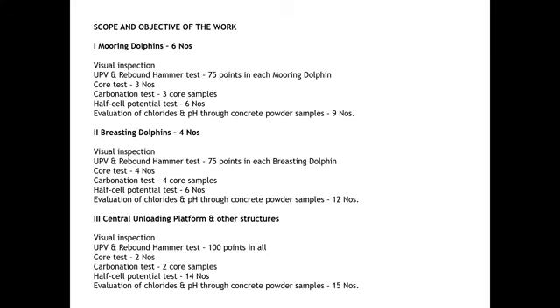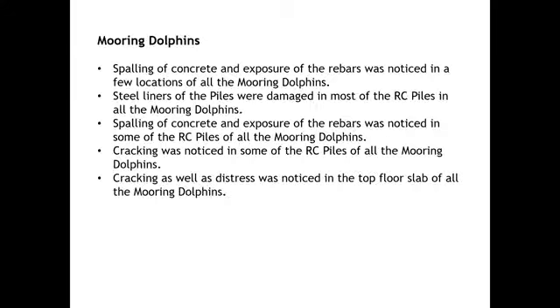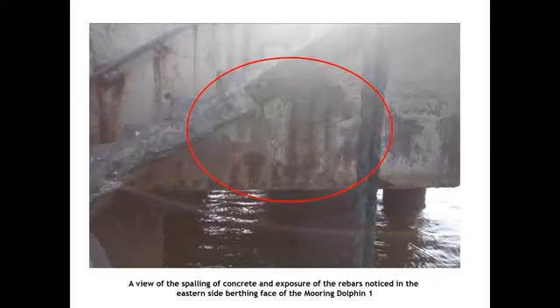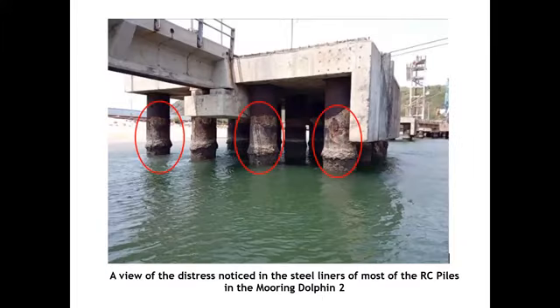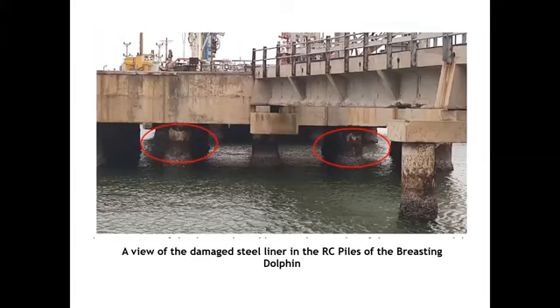So for the different structures, you decide the numbers, and then you go for a visual observation, and check whether spalling is already taking place or only cracks have formed. Suppose you have a steel liner: what was the original thickness of the steel liner, what is the thickness now, and should we maintain the same steel liner, or remove it completely and redo it? For example, here the stirrups are visible. This is the steel liner condition. You can find the steel liner is completely gone, and even the stirrups are visible on the outside.